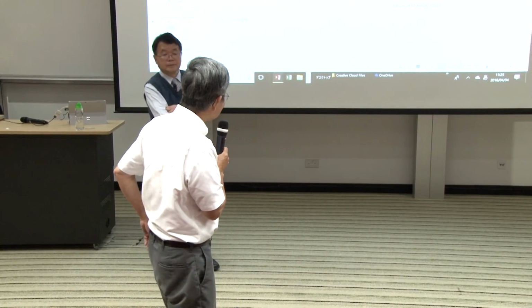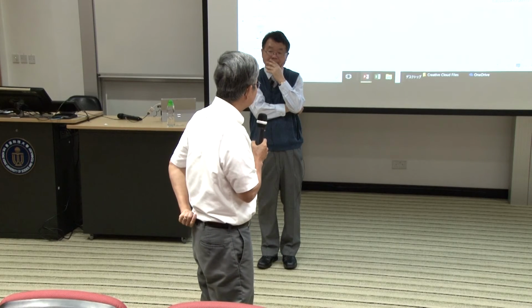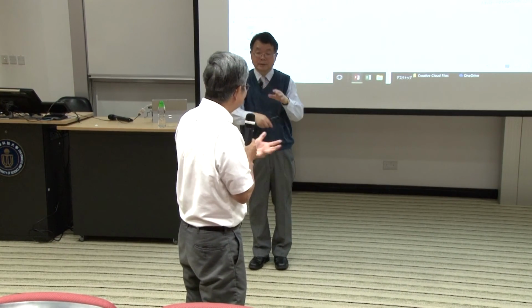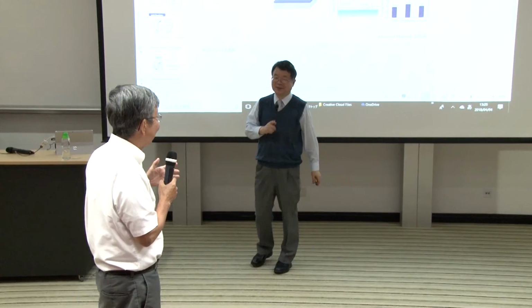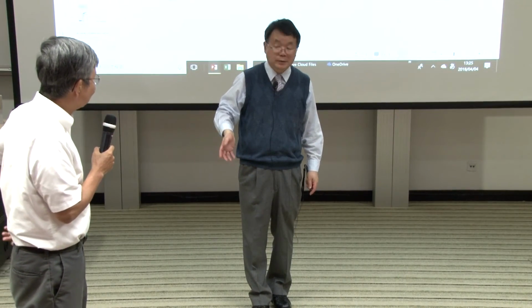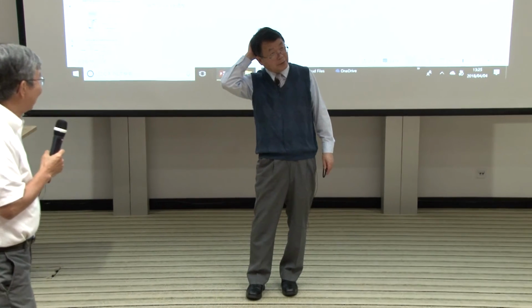I'd like to ask a question. You say you have this calcium oxide composite that has a work function of 3.1 electron volts and is air stable. That's rather amazing, because magnesium and lithium are all unstable. Exactly how stable is stable? If you leave it out in air, does it get oxidized and the work function go up? No, it doesn't change at all. What about heating? Up to 200 degrees, maybe no problem.